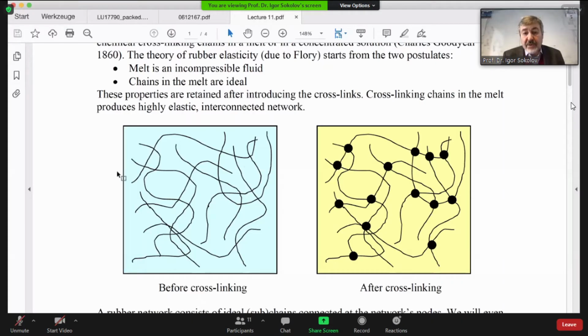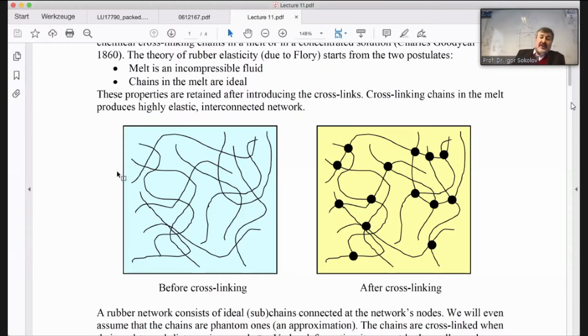Now, the explanation is too simplistic, but of course there is a theory by now for this, and there were also experiments. You can take the chain and have a look at the conformation, at the end-to-end distance, at gyration radius, and people have seen they are indeed ideal. When Flory started, nobody believed him, but then people started to believe because they have seen.